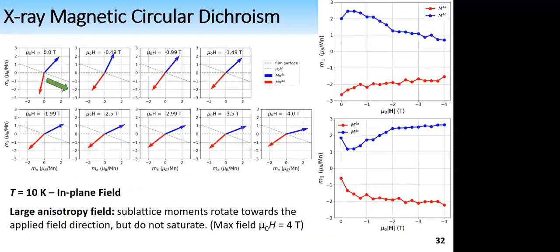Now that we know that this method works, we can consider the in-plane measurements with field in plane. Here we've applied a field up to 4 Tesla along this direction. And what we notice is that the sublattices haven't switched, so they haven't saturated along the field. So the first clue is that there is a large anisotropy field.